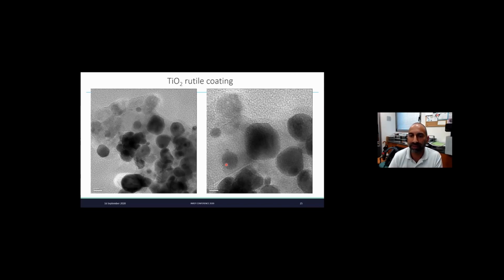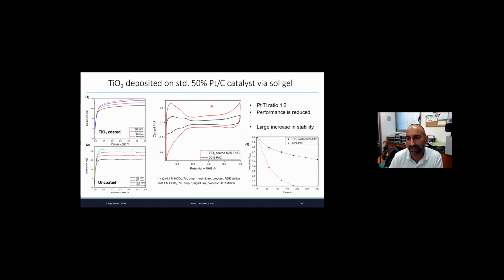So it did coating of Titania, which on top of platinum, this is platinum and this is Titania. So he did that. And by doing that, he increased the stability of the platinum by a very large factor that I don't know how to calculate because the platinum is really, the performance is going down very rapidly. And the Titania is still doing well after a few minutes into the electrolyte, the hot electrolyte, which is really a very, very aggressive test.